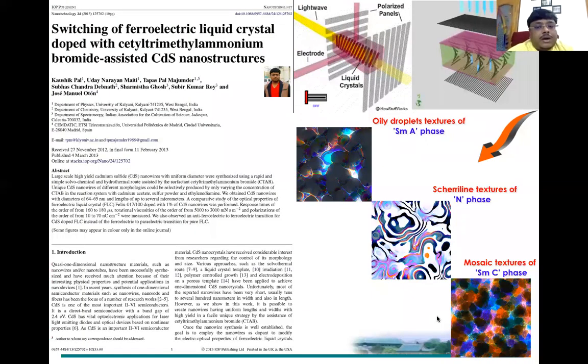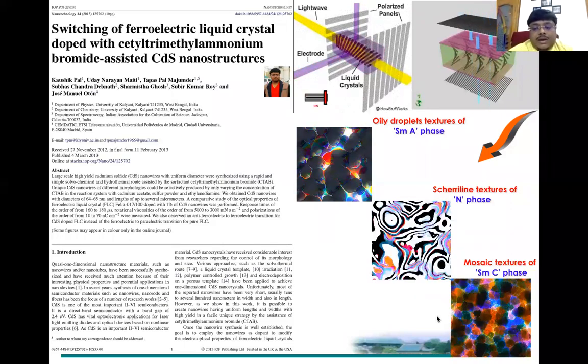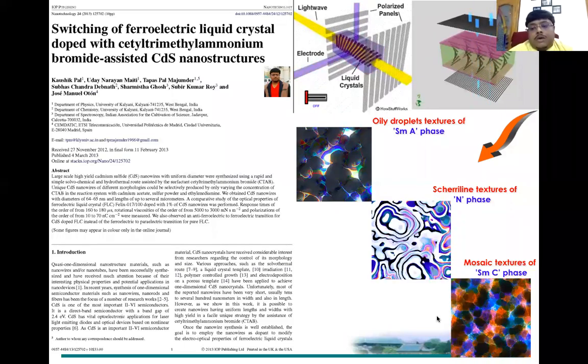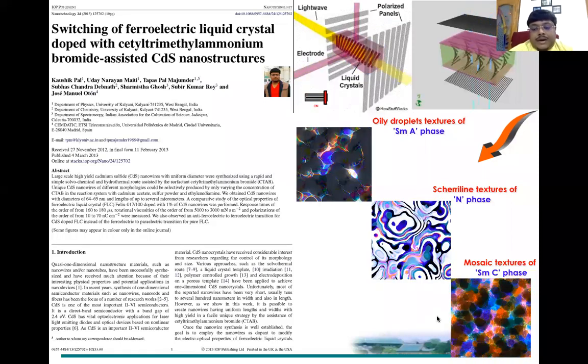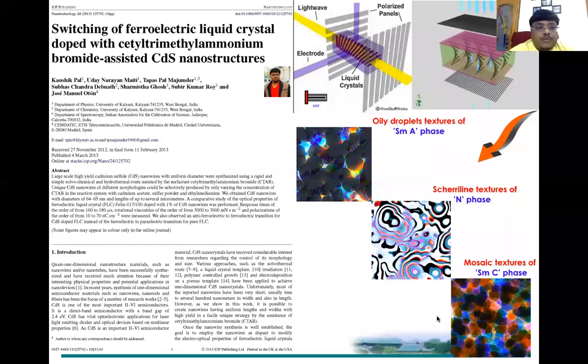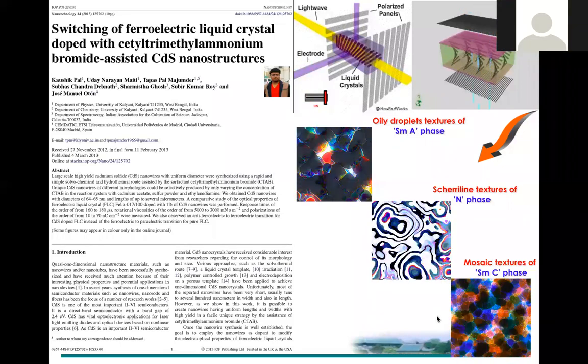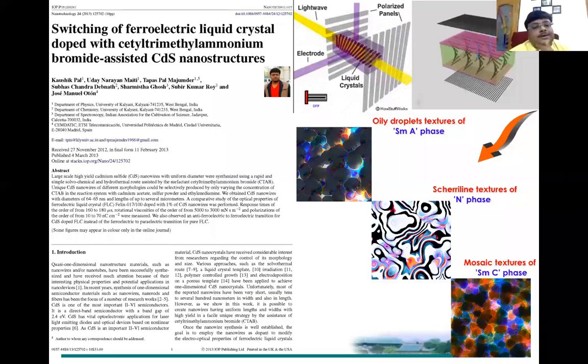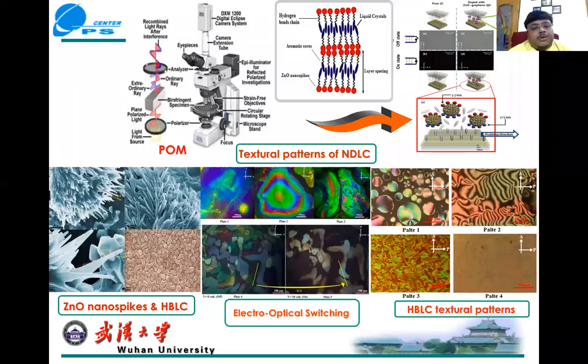So this I published in IOP Nanotechnology, and there are several types of droplet-like structures, schlieren patterns, and marble-like patterns. With this switching phase, we applied our work in IOP Nanotechnology. This is polarizing optical microscopy, and under this microscopy we can utilize our samples for the characterization of switching. You can see plate one at the right side is a droplet, then a schlieren pattern, then a broken fan, and lastly plate 4 is a worm-like structure. And you can see the electro-optical switching in the middle. How is the switching captured under the polarizing optical microscopy?